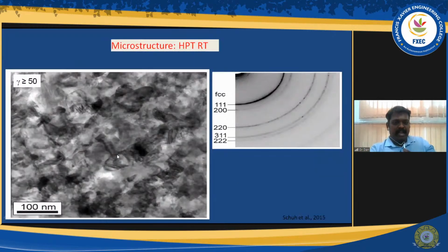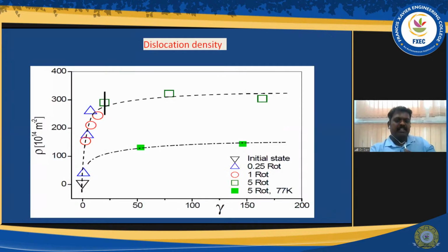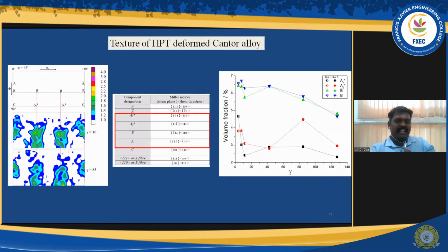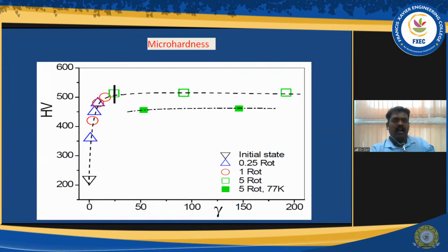Here I showed some TEM images. The TEM images clearly show the very fine structure, 25 nanometers. You can also see the dislocation density increasing with the number of cycles. As for texture, I already told you that any process will lead to a characteristic texture evolution. Here we are mainly doing a shear process, so shear related texture components evolve. If you take B bar and A star, these are shear related components. As expected, these shear related components increase in this alloy, but the texture is not strong. It's really very weak.